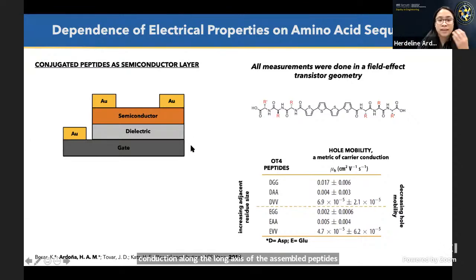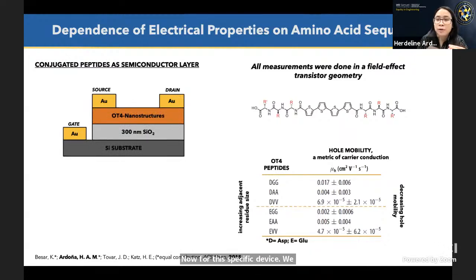A schematic of the device is shown on the left, wherein we have three electrodes. You have source and drain electrodes spanning the semiconductor, and then a gate electrode, whereby the gate layer helps shape the current flow occurring within the device. For this specific device, we used our peptide OT4 nanostructures in the semiconductor layer. And the measurements showed that as the adjacent amino acid size increases, we also see a trend in the measured hole mobility,